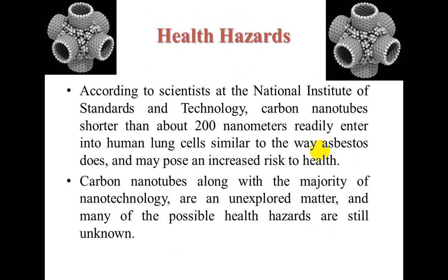Health hazards. It is an important aspect of life, so we see the use of CNTs in health fields. According to scientists at the National Institute of Standards and Technology, carbon nanotubes shorter than about 200 nanometers readily enter into human lung cells, similar to the way asbestos does, and may pose an increased risk to health.